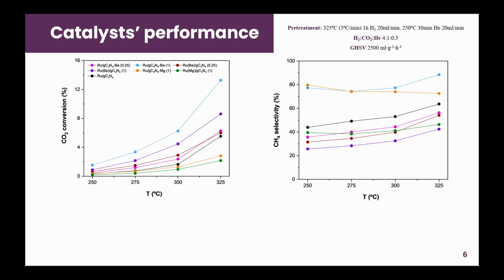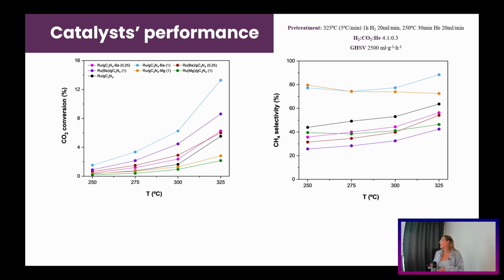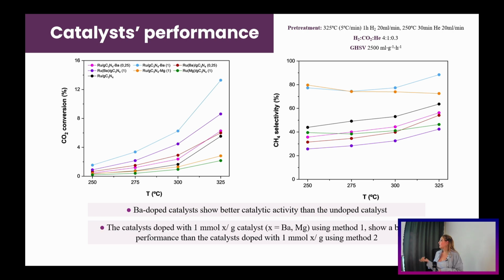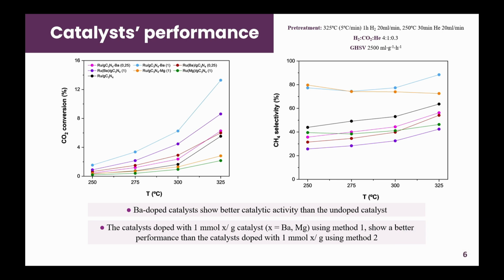And these are the results of the catalysis performance. We obtain a higher catalytic activity with the barium doped catalyst compared to the undoped one. And also we obtain a higher catalytic activity when doping using the first doping method, mixing the alkali and the urea before the polymerization, for both barium and magnesium. And moreover, the methane selectivity was also higher using this first doping method.